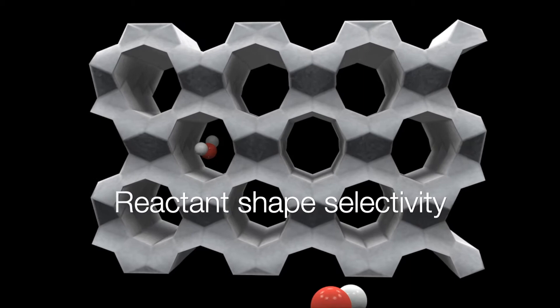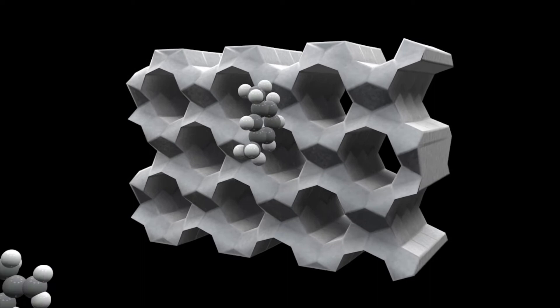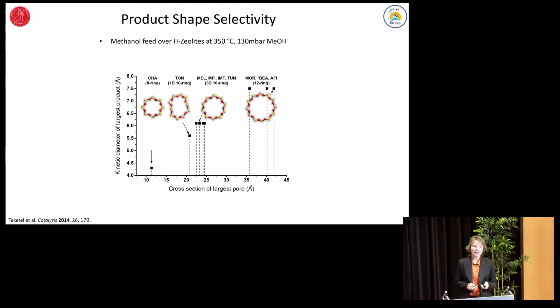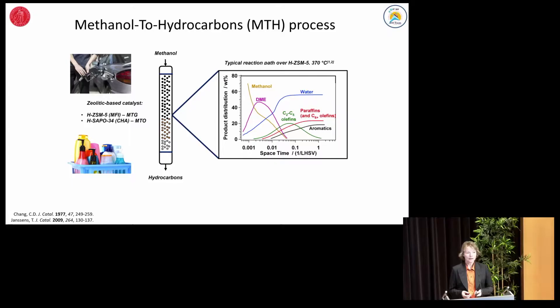Microporous materials, here exemplified by a zeolite, are molecular sieves. The sieving effect contributes to their shape selectivity, since only reactants with diameters smaller than the pore size are allowed to enter the pores. Furthermore, a direct correlation is observed between the size of the largest product formed in the reaction and the largest pore diameter. Products with larger diameter are occluded in the cavity where they are formed and may undergo further reaction towards smaller molecules or, eventually, coke.